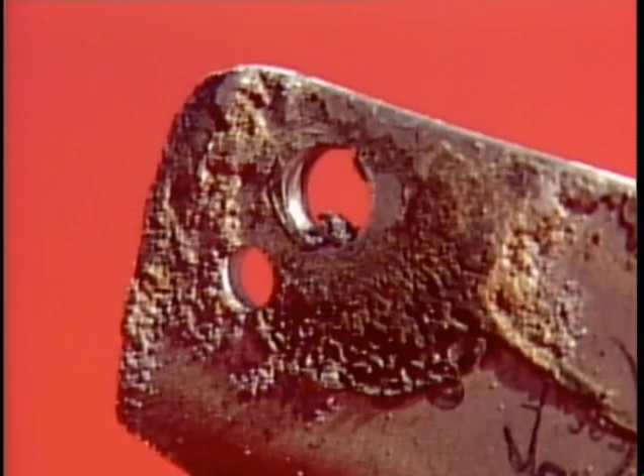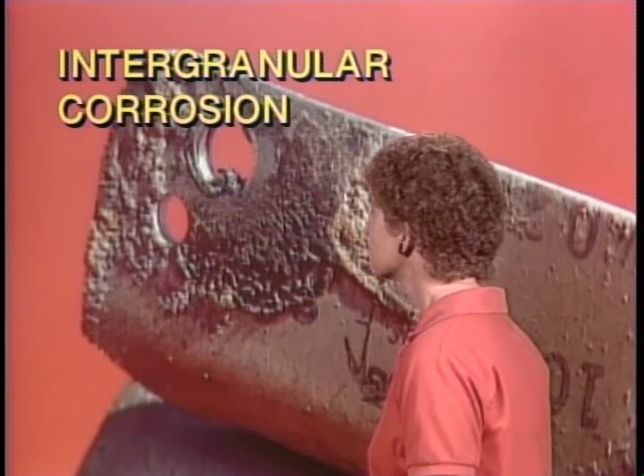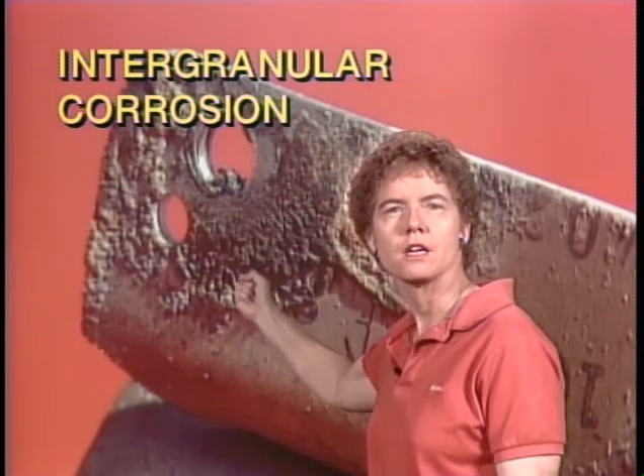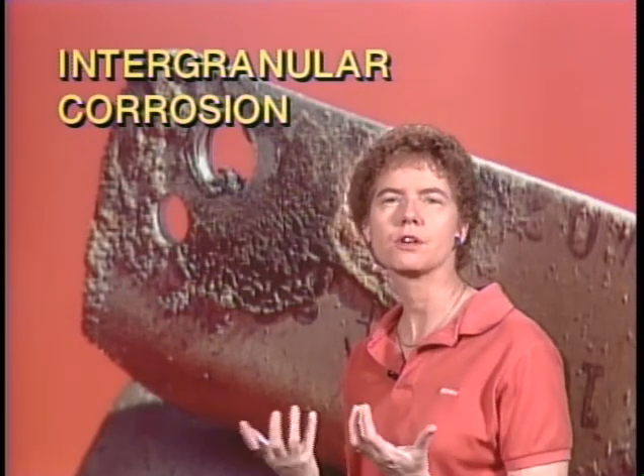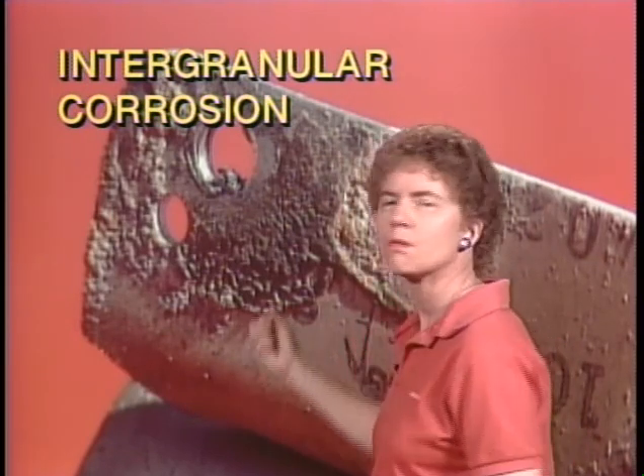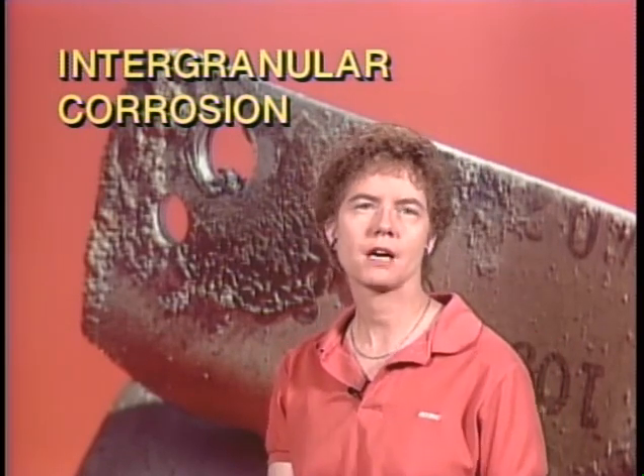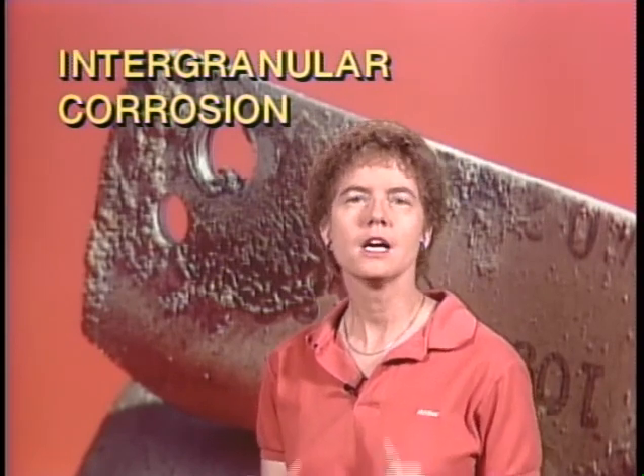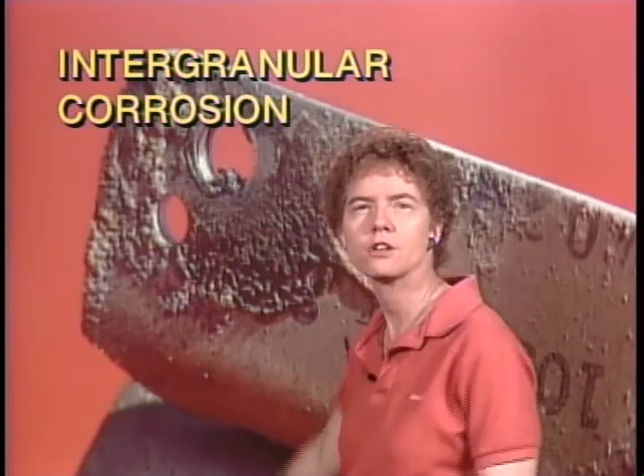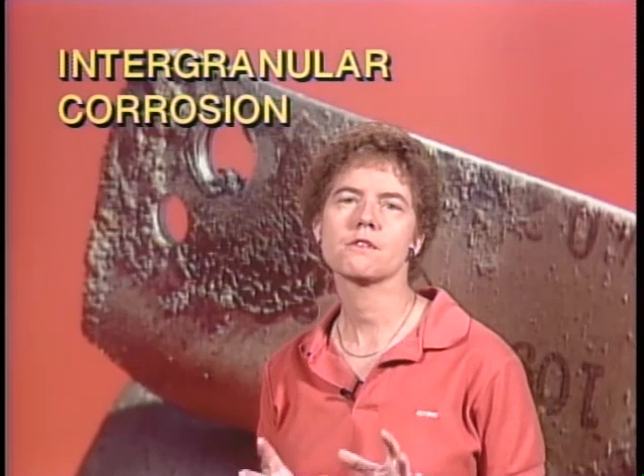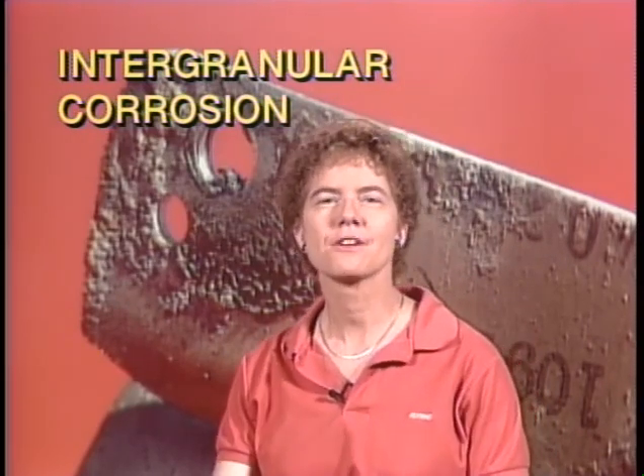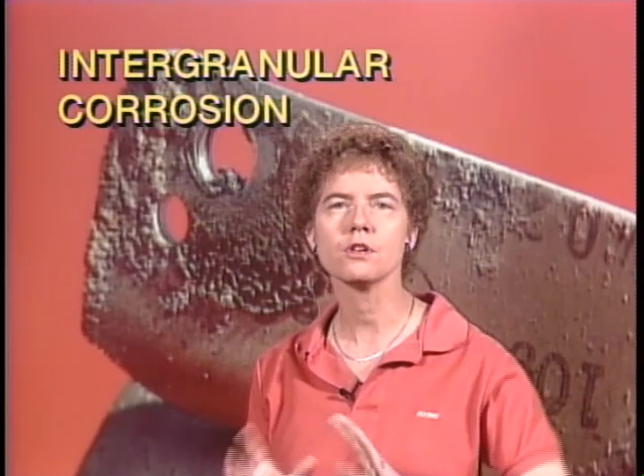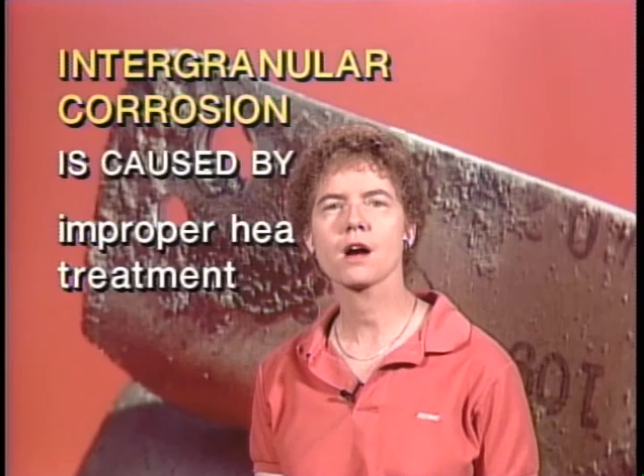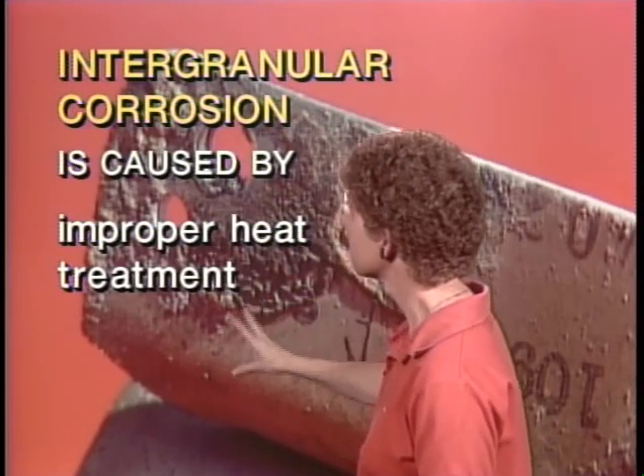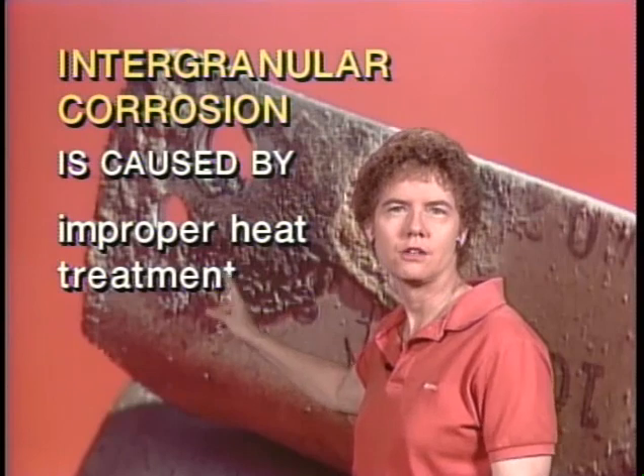Let's talk now about intergranular corrosion. This is an example of intergranular corrosion, and basically what happens with intergranular corrosion, or delamination of the grain boundaries, is that the corrosion is attacking along the grain boundaries of a metal alloy. Typically, this kind of corrosion results from a lack of uniformity in the alloy structure. And the reason that the alloy does not have uniform structure is because it was improperly heat treated. So intergranular corrosion is caused by improper heat treatment.